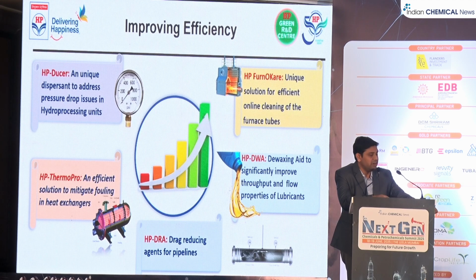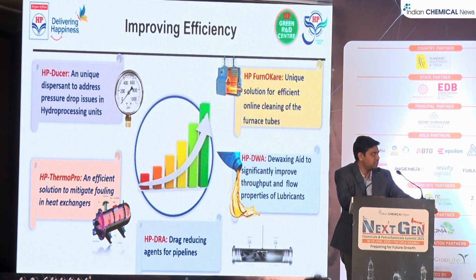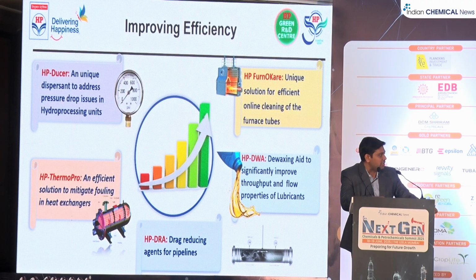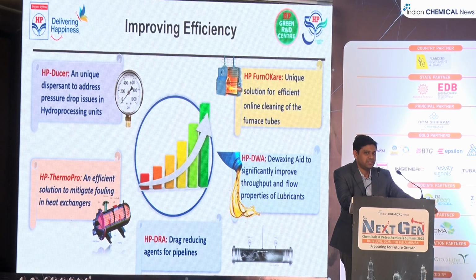Then there is HP FurnOKare, which is basically our solution. This is a services plus product offering from HPCL. Here, if due to deposition of non-conductive materials on the coils in the furnace, we see a higher bridge wall temperature, it helps us to reduce the bridge wall temperature, and in turn, it improves the efficiency of the furnace.